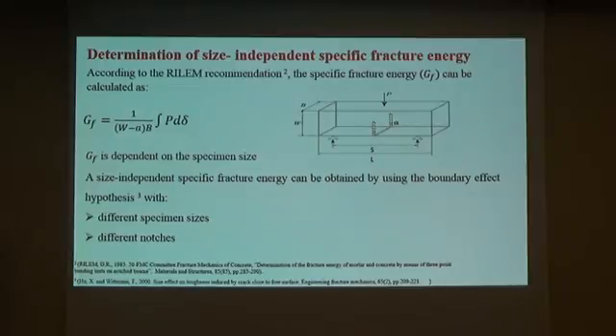As I mentioned before, I will talk about the main properties of fracture energy. The first one is the size-independent fracture energy. According to RILEM recommendations, the specific fracture energy can be obtained from the work of fracture based on the notched three-point bend test, and by using this equation, the obtained specific fracture energy is dependent on the specimen size.